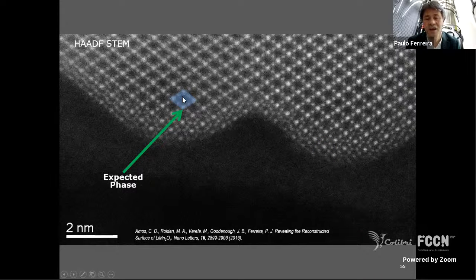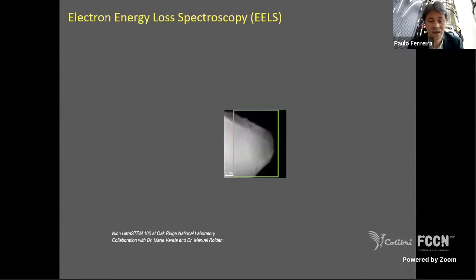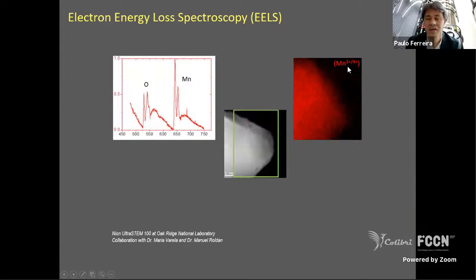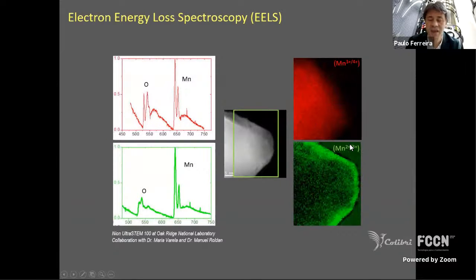You see that in the middle of the diamonds, you have 2 atomic positions filled. That means that the structure has been changed at the surface. So this is an example of using the atomic structure to understand that something has changed. And when we use EELS, another technique, a spectroscopy technique in the microscope, we realized that in the bulk, the manganese had valence states between 3+ and 4+, but on the surface, the manganese had 2+ and 3+ valence states. So we know now that these atomic positions were filled with manganese with a valence state of 2+. And we can get this right now at the atomic scale.